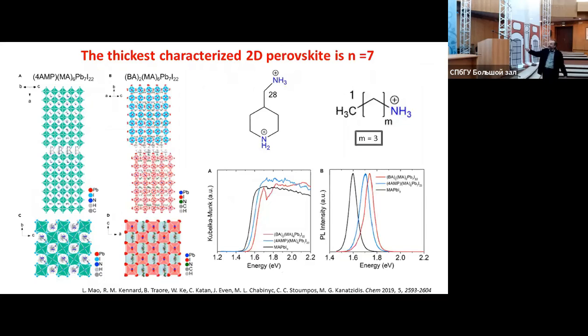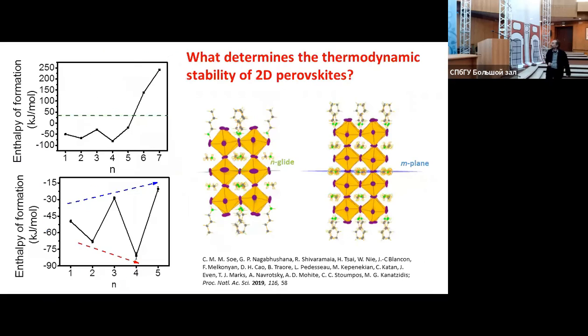We continued, though, and tried to solve some structures, and we hold the record now: 7-layer perovskite. These are massive unit cells. The unit cell itself is 10 nanometers. This layer is 5 nanometers, to give you a scale. And we see that as we go so high in thickness, we're approximating the optical properties of the bulk perovskite.